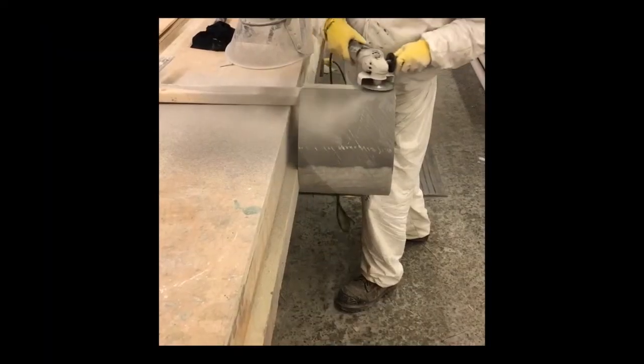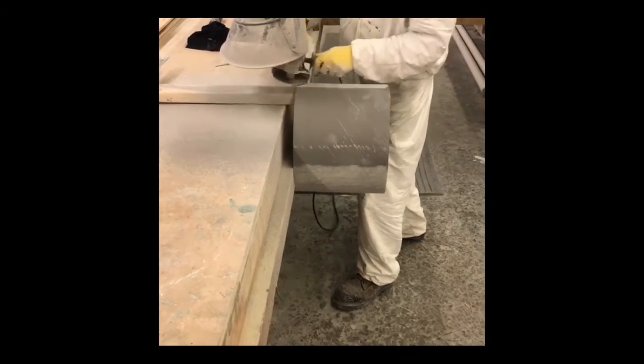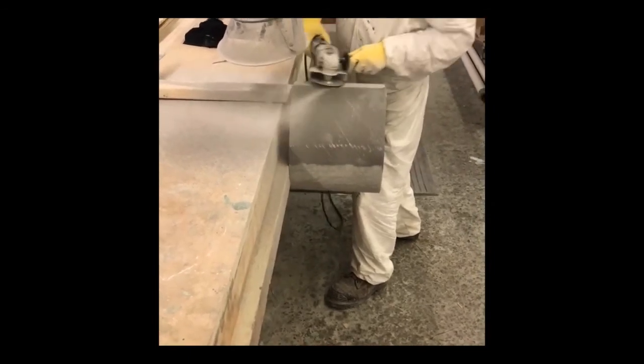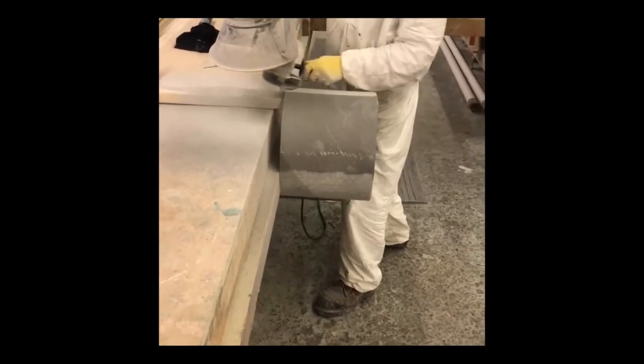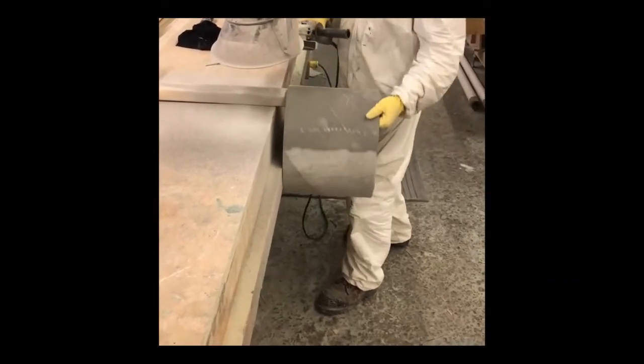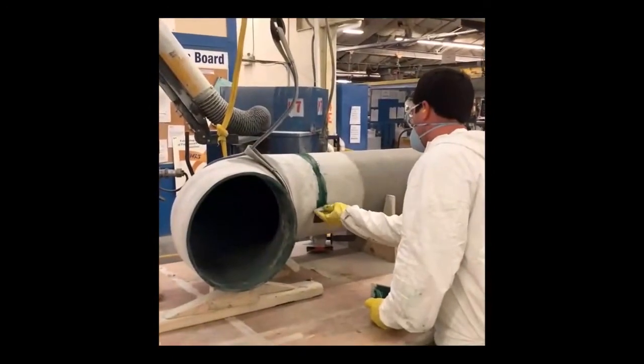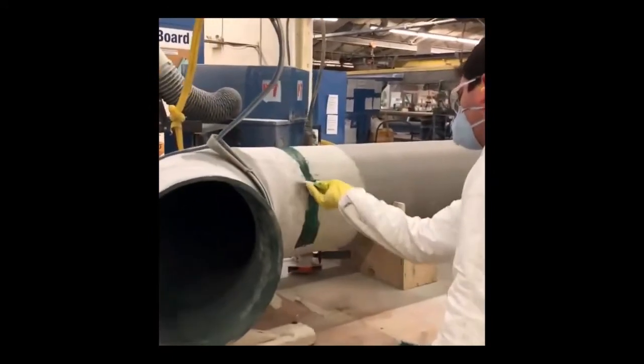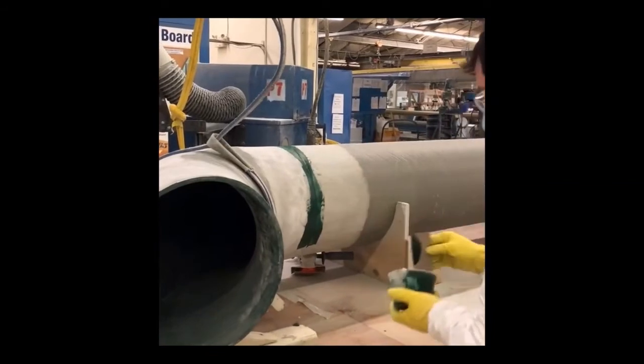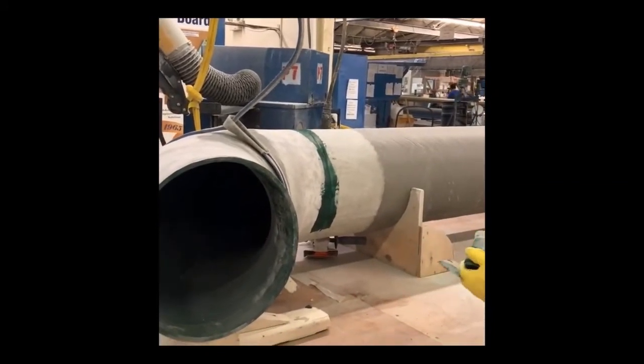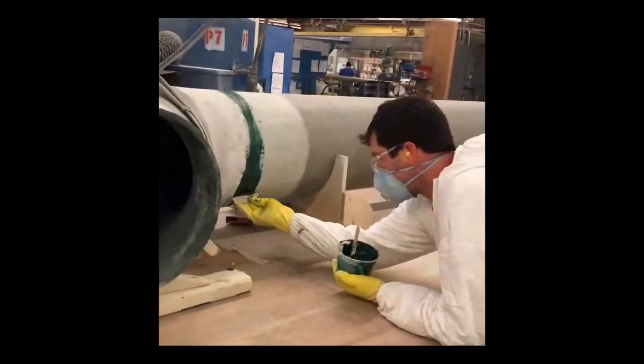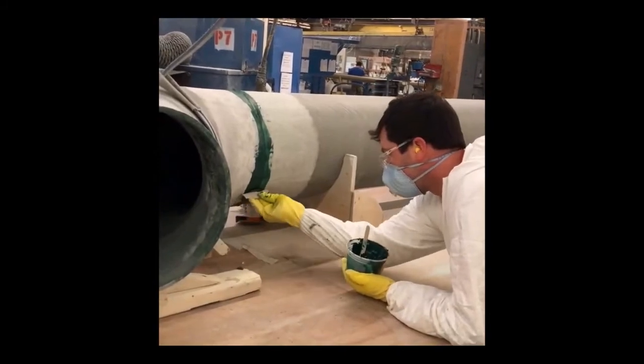So in this case, the technician is grinding off that wax brush coat. He's got to make sure he gets all of that off because, as I say, it has wax in it and you won't get a good bond to it. So the technician grinds off all of the wax top coat and then he liberally applies that crevice paste to the crevice. He's fit the pieces of pipe together. He liberally applies that crevice paste. He's got it all in, filling in all the little nooks and crannies.